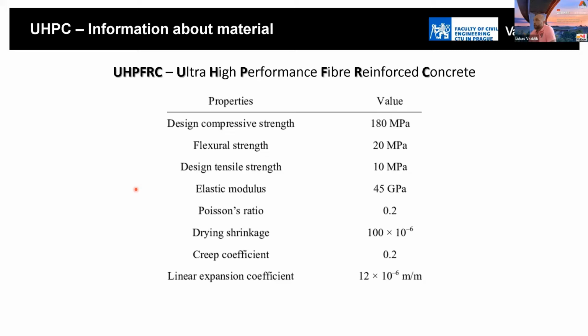Important is the question about creep and shrinkage. About creep, we have a very small coefficient. That means it is possible to say that the creep could be neglected in some special arrangements and types of analysis. So the creep is very low, again, compared to normal concrete. Normally, for shrinkage, we have only drying shrinkage, so only in the initial stage of the behavior of the concrete. So it is important, for example, during the casting of the element. But after a few days, it is possible to see that no shrinkage will appear on the structures.